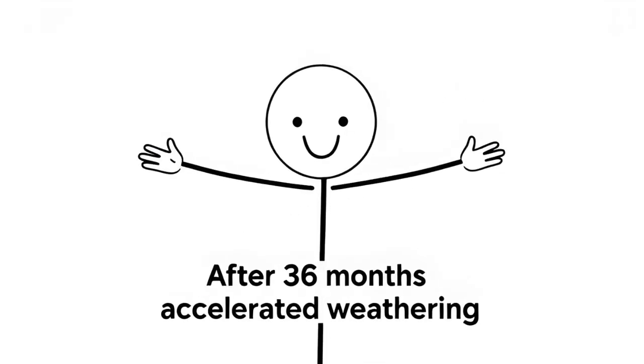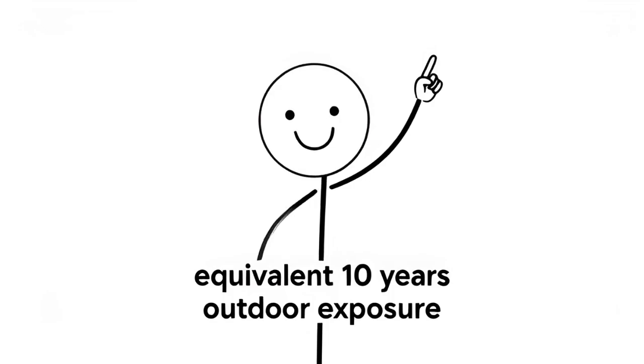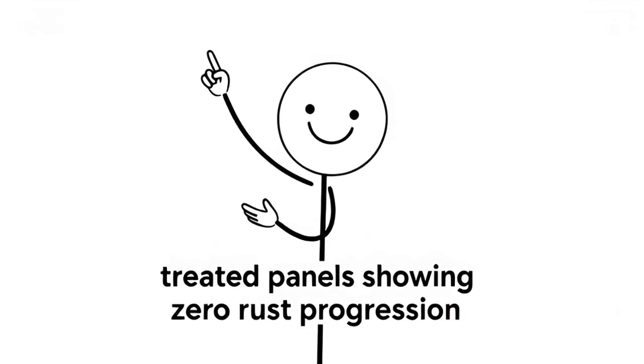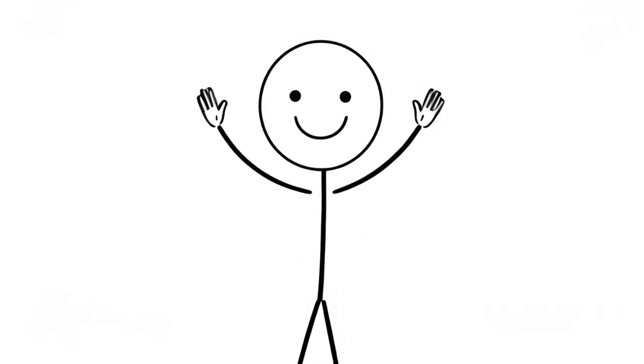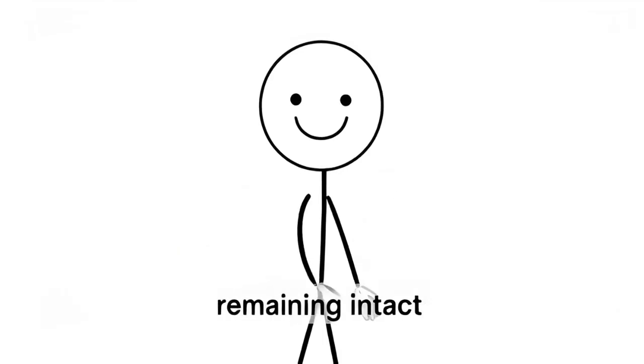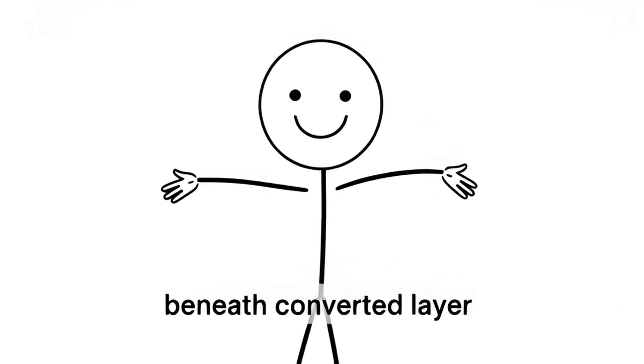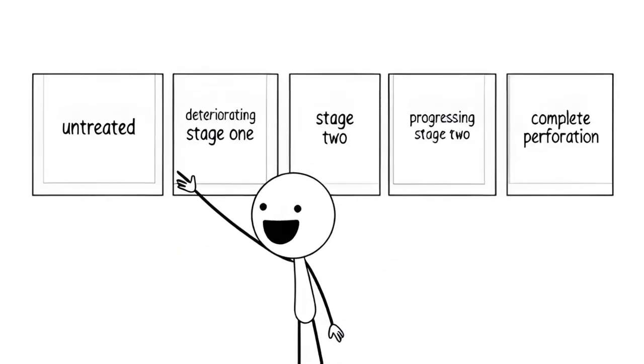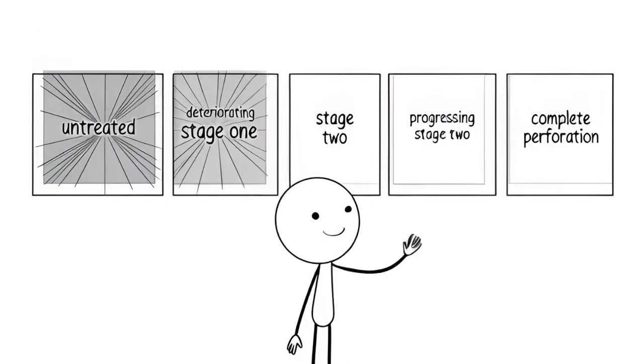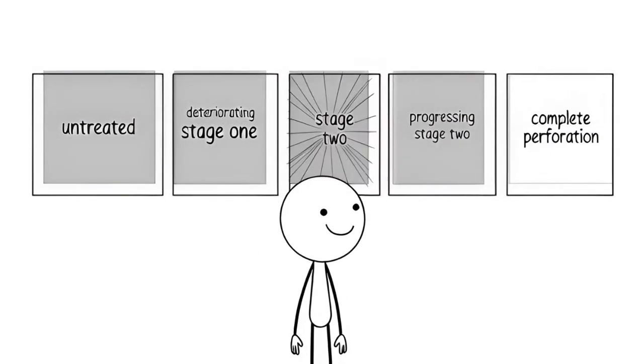After 36 months of accelerated weathering equivalent to 10 years of outdoor exposure, the treated panels showed 0 rust progression. The iron phosphate coating remained intact with no measurable corrosion beneath the converted layer. Untreated panels continued deteriorating, with Stage 1 progressing to Stage 2 and Stage 2 progressing to complete perforation.